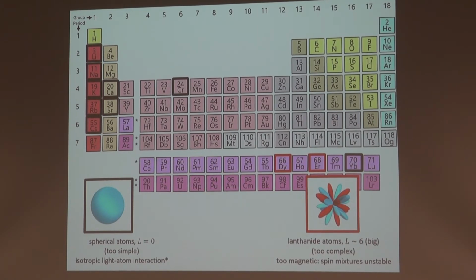One can create spin-orbit coupling through anisotropic light-atom interactions, where the polarization of light and the spin state of the atom both have to be factored in figuring out how strong the light-atom interaction is. We can realize that for these closed shell atoms, but only by going very, very close to atomic transitions where we can gain some of the spin-orbit coupling of the excited states.